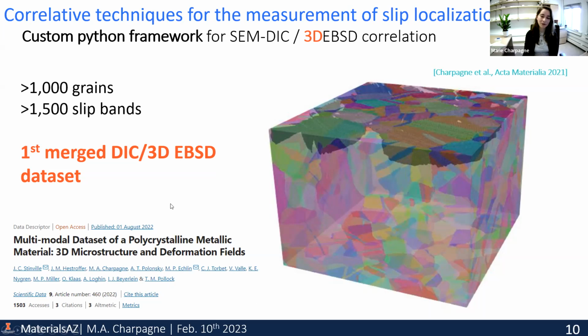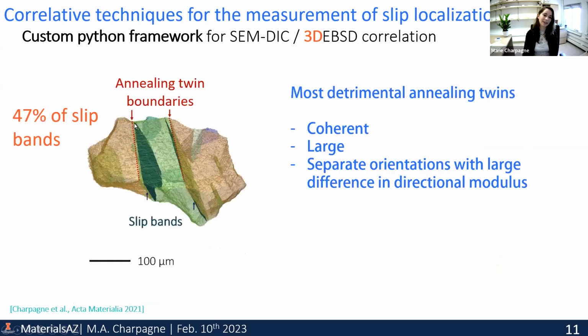And so what we found with this kind of merged DIC and 3D EBSD dataset, well, we can now look for the first time at slip bands in 3 dimensions. And we found that a large fraction of those slip bands actually develops near specific boundaries that we call twin boundaries. These are particular boundaries that form in any FCC material upon annealing, so that's where their name comes from. They're very flat boundaries, and they separate two crystals that are within a particular twin relationship.